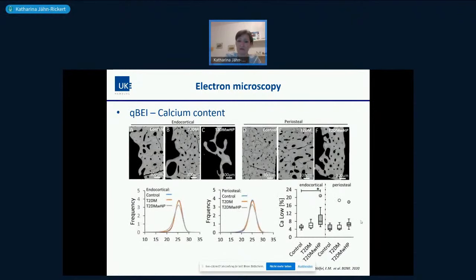Electron microscopy, if used as a method of quantitative backscattered electron imaging, can also determine the calcium content, so like the true content of calcium within the mineralized bone matrix. And here I would like to show some data from my colleague Eva Maria Wölfel, who just recently looked at type 2 diabetic specimens compared to individuals that were age-matched and didn't suffer from type 2 diabetes. And there, with this disease, type 2 diabetes, we also have a high fracture rate that cannot be explained easily by this bone mineral density measurement that I mentioned in the beginning.